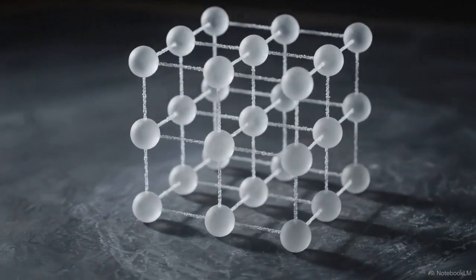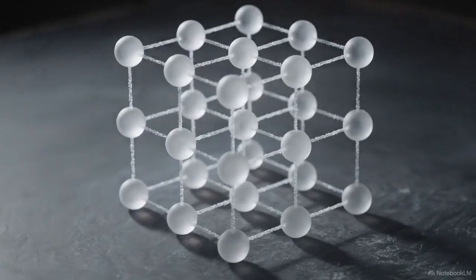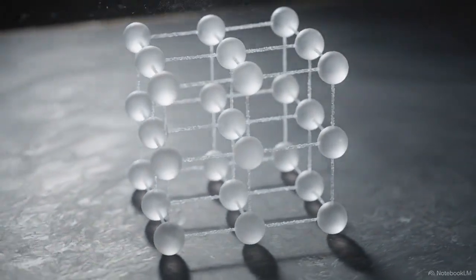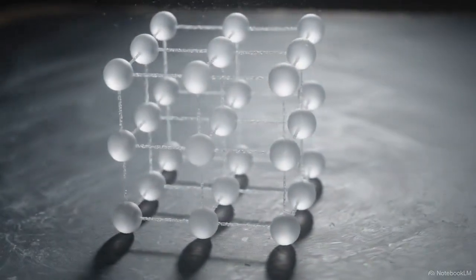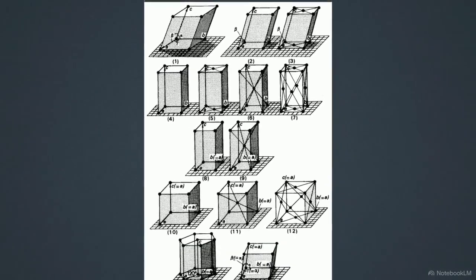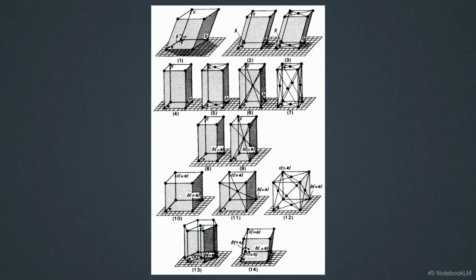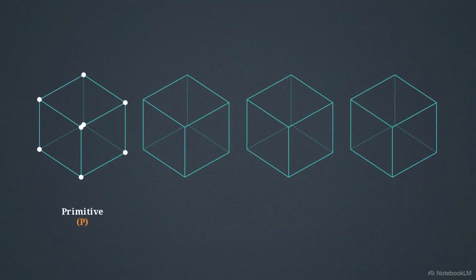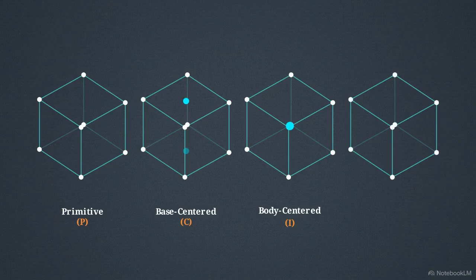By making symmetry the primary selection criterion, non-primitive centered cells become a mathematical necessity for capturing a lattice's true structural class. This chart displays the full numbered array of the 14 Bravais lattices. Expanding the symmetry rule into 3 dimensions strictly limits all possible periodic arrangements to these specific forms. The 14 configurations distinguish between standard primitive cells and centered variations, including cells centered on a single pair of opposite faces, on the body center, or across all faces.